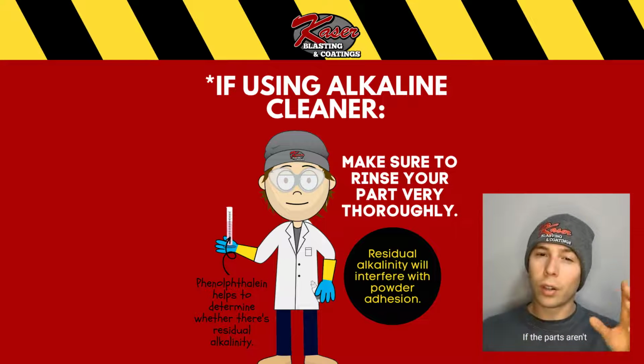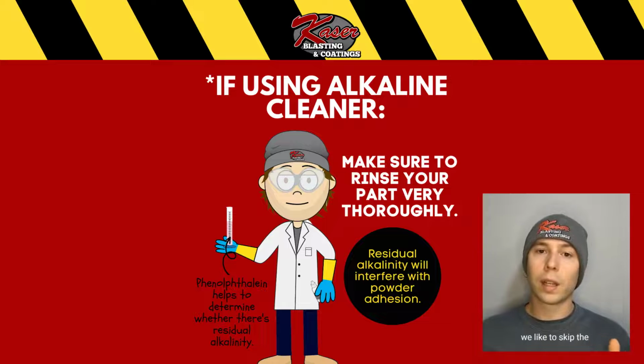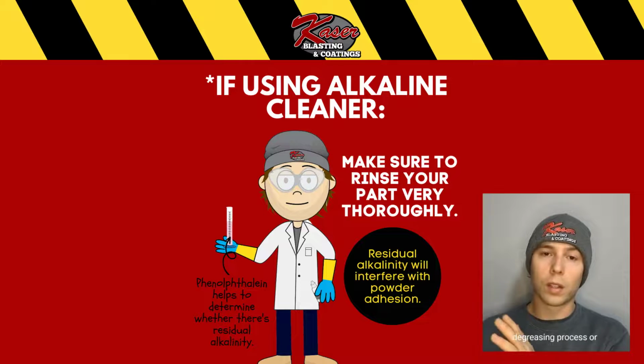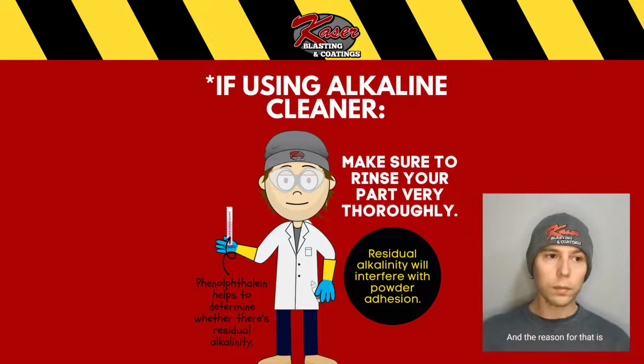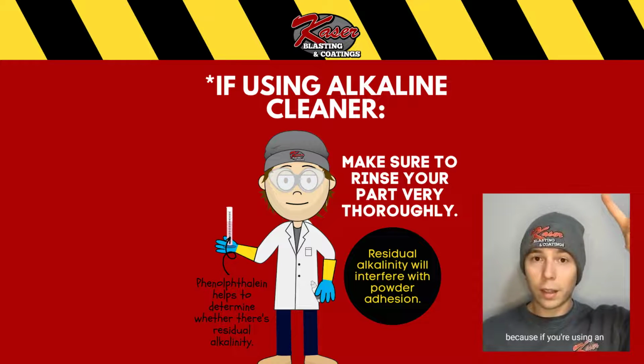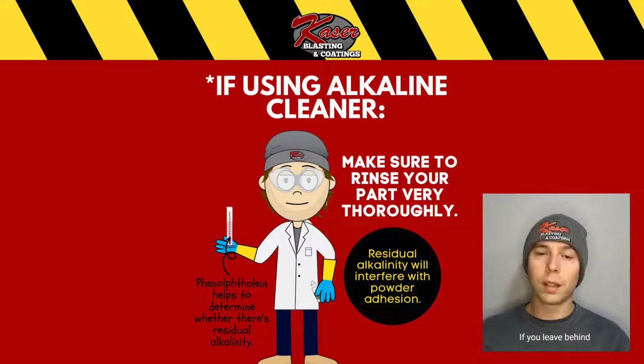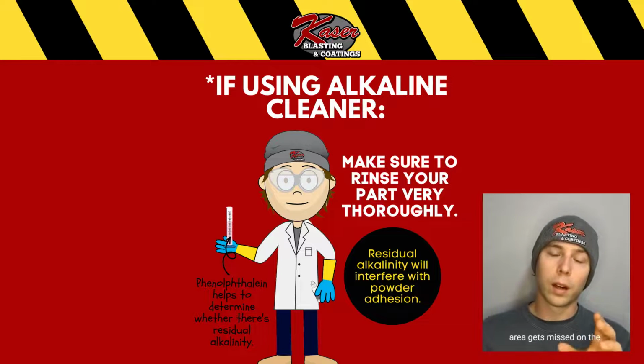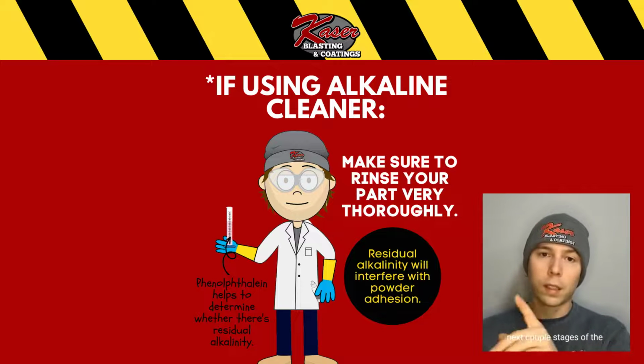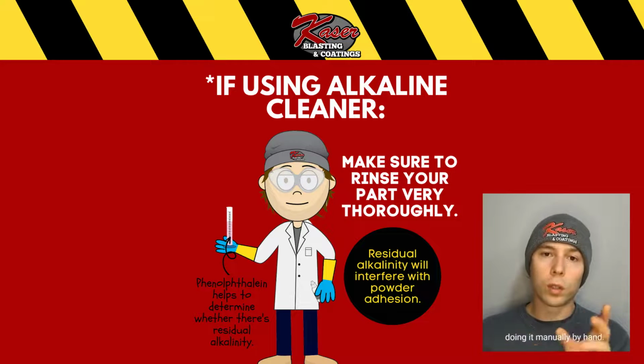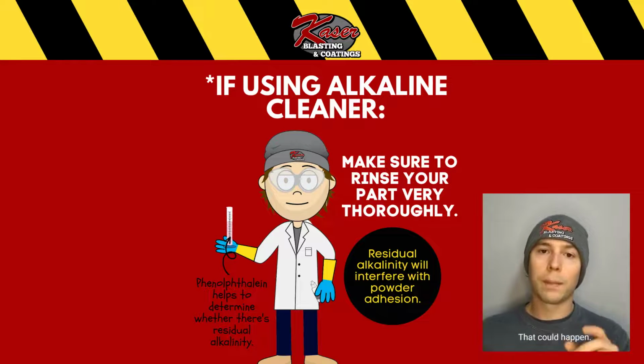If the parts aren't really oily and greasy, then typically at Kaiser we like to skip the degreasing process or the alkaline cleaner. And the reason for that is because if you're using an alkaline cleaner, you have to be very, very careful. If you leave behind alkaline cleaner on a part, meaning it just doesn't get rinsed well enough, an area gets missed on the next couple stages of the pre-treatment when you're doing it manually by hand, that could happen. And so you have an area that just has alkaline cleaner on it.